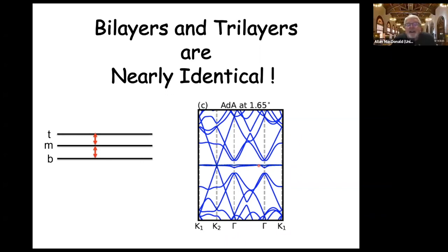Yeah, so the density of states in this highly dispersive odd parity band is so low, I think it just doesn't matter for the superconductivity. Okay. So the point is that we should really only care about the flat band, and whether it's isolated from other bands doesn't matter, especially because it's a Dirac cone, which has negligible density of states at that point. Yeah. So over this width of gating that we've been talking about, of a density of a few times 10 to the 12 or something, the Fermi level gets pinned in these flat bands.